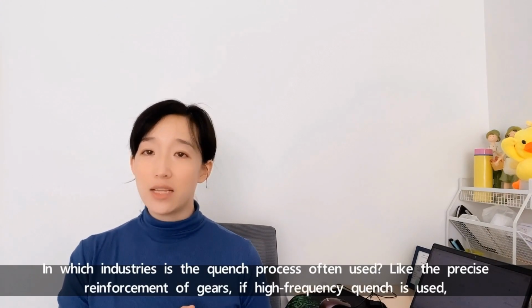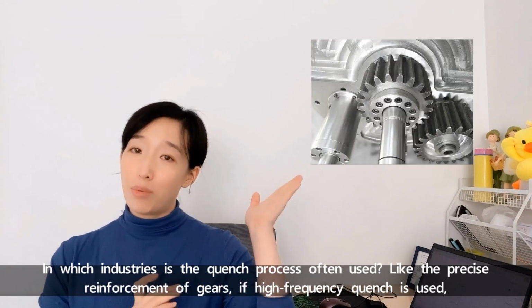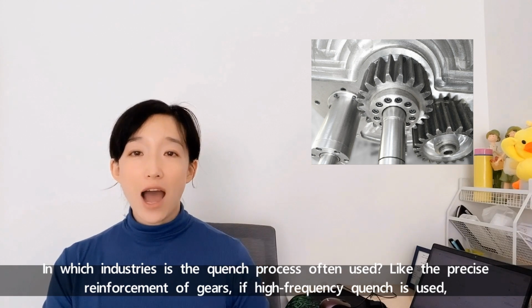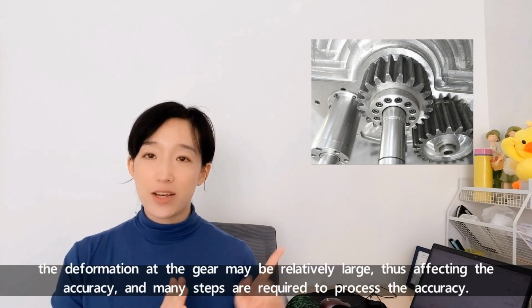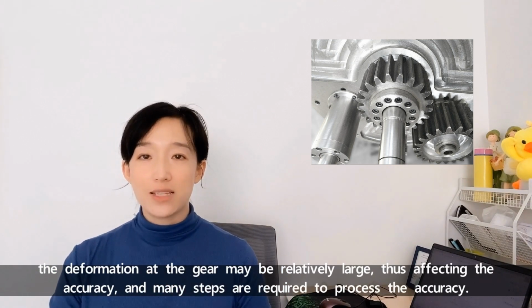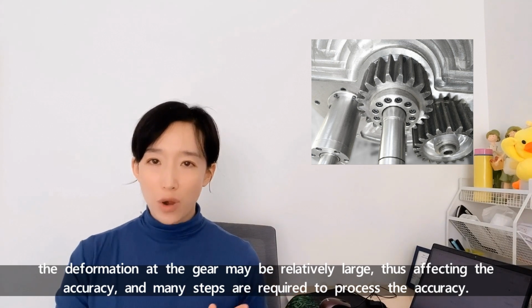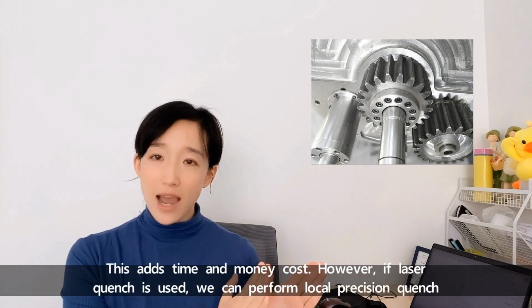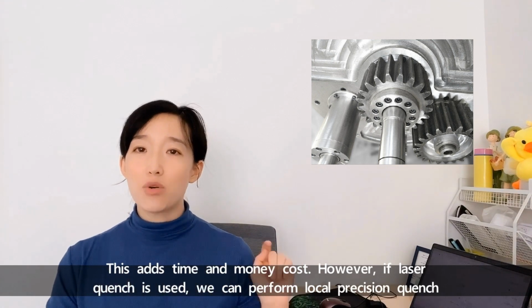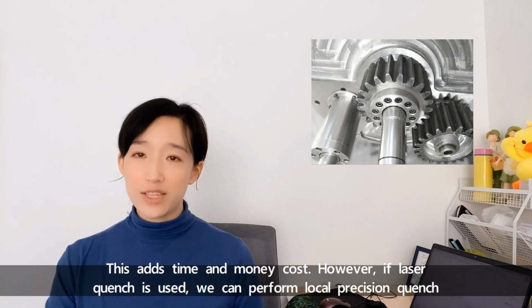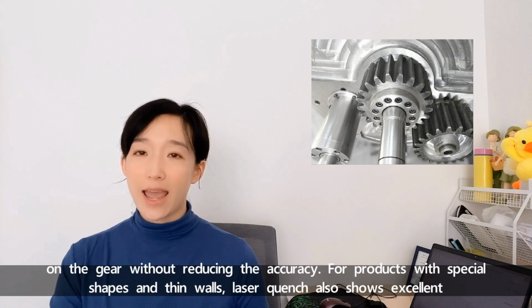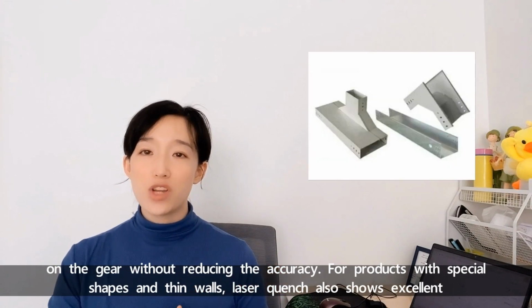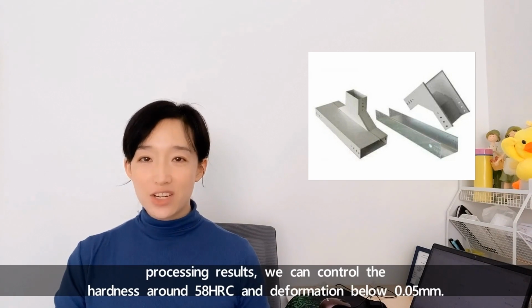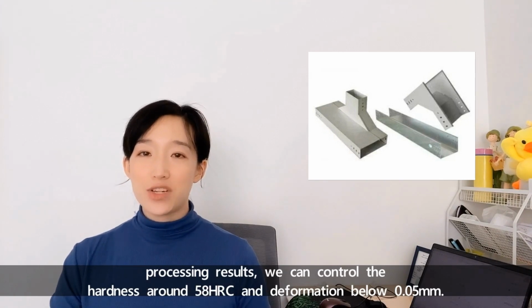In which industries is the quench process often used? Like the precise reinforcement of gears, if high-frequency quench is used, the deformation of the gear may be relatively large, thus affecting the accuracy, and many steps are required to process the accuracy. This adds time and cost. However, if laser quench is used, we can perform local precision quench on a gear without reducing the accuracy. For products with special shapes and thin walls, laser quench also shows excellent processing results. We can control the hardness around 58 HRC and deformation below 0.05 mm.